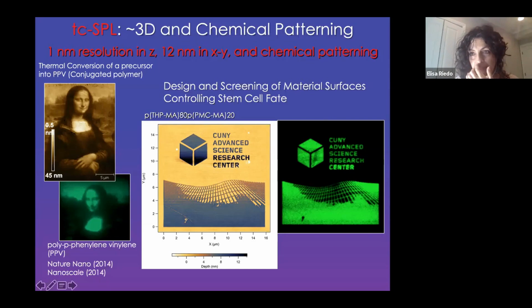And this is the chemical image. So it shows that where you have heated, you see this is deeper, right? The topography is indented. So you have heated more here. Well, there are also more amine groups here. So the fluorescence is higher.